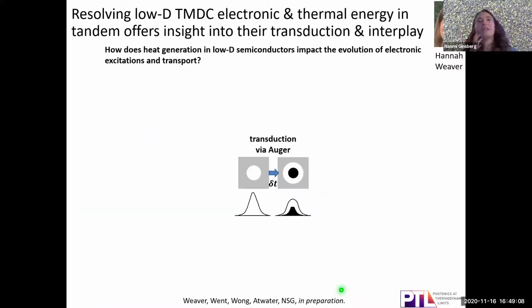All right, so onto the simultaneous presence of electronic species and heat. Generally, those of us who use pulse lasers are keenly aware of the fact that we might be unintentionally imparting heat to an electronically excited semiconductor through higher order processes like annihilation or Auger recombination. It can be challenging to tease apart electronic and thermal contributions to an optical signal, and it's especially important in low dimensional systems like few or monolayered transition metal dichalcogenides, because heat that would otherwise disperse in 3 dimensions is confined to fewer dimensions. So this really begs the question of how does heat impact the electronic evolution, or possibly also masquerade as it.